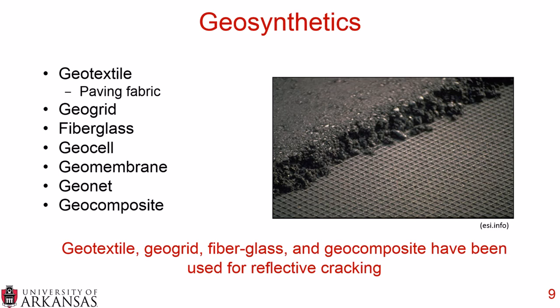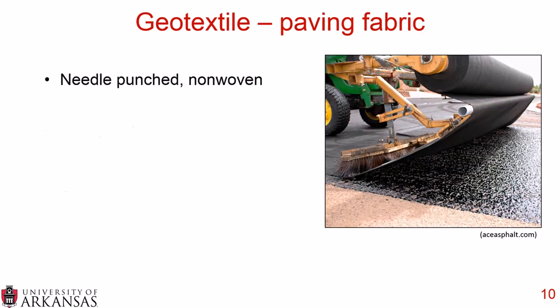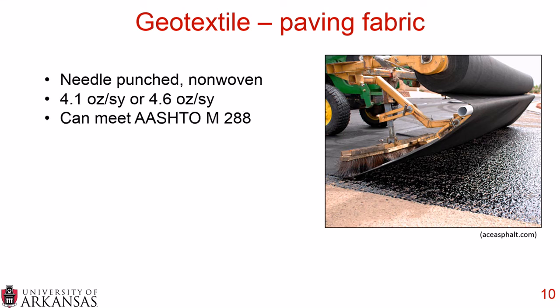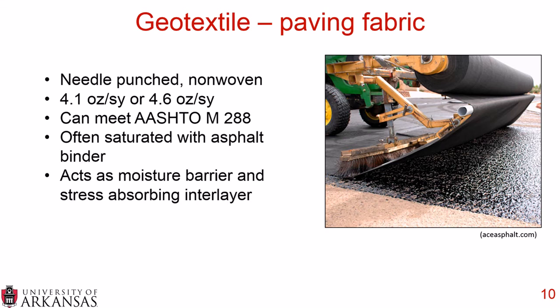And when we think specifically of pavements, geotextiles, geogrids, fiberglass, and geocomposites have been used for reflective cracking. So as you're reviewing literature, you'll probably see these types of geosynthetics mentioned. So for example, for paving fabrics, this is needle punched and non-woven. It's 4.1 ounces per square yard or 4.6 ounces per square yard, depending on the thickness of the fabric you're laying. And you want it to meet AASHTO M288.